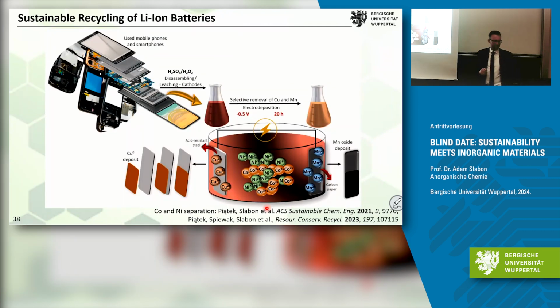So we took real batteries. And this is my first advice: use real battery waste, because simulated solutions make some problems. We leach the critical raw elements, and then we have a solution with copper, nickel, cobalt, manganese, and then we applied electrochemistry at room temperature. We used a steel electrode and a carbon electrode, and applied a potential of -0.5 volts.